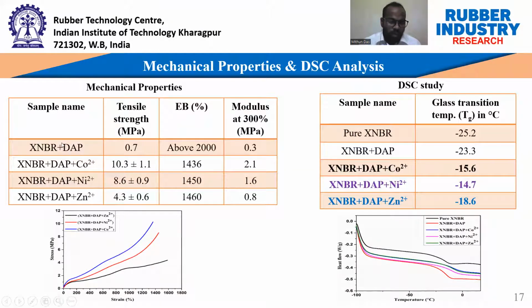Without metal ion, the DAP modified compound alone has a very poor tensile strength, 0.7. After addition of metal ion, the mechanical properties also increase. In the case of the cobalt system, the tensile strength is 10.3, in the nickel system it is 8.6, and in the zinc system it is 4.3. And this is the stress strain plot of the various metal ligand modified rubber compounds.